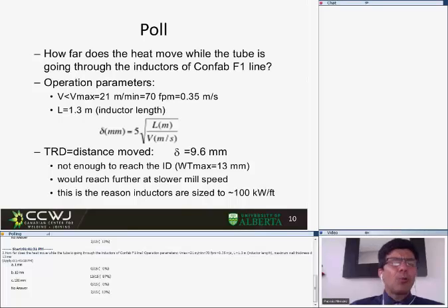Although we all knew that with bigger distance or smaller velocity, things start to get better and the heat propagates, we see that it's not proportional. We have this other effect that means a 20% decrease in velocity would buy us only a 10% increase in thickness.